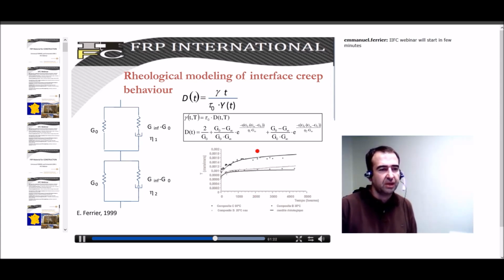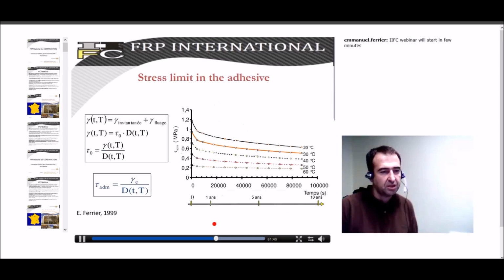At the end, what is interesting is that if you use some specific rheological model, you can fit your parameters in comparison with the experimental data we get. Using this, you are able to get the shear strain evolution depending on the initial shear stress and the creep function you have. What we imagined with this is that the creep strain, the shear strain, depends on the instantaneous strain and the creeping one. It means that if you identify the initial shear strain you have in the adhesive, if you apply a constant stress, and if you know how this strain will change during time, you are able to fix the minimal value of shear stress you should have in the adhesive to keep your lap joint elastic.